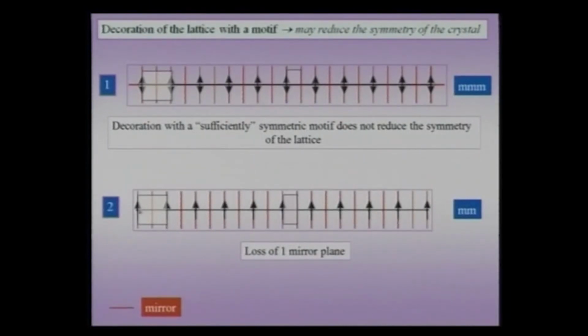Vertical mirror 1 remains, vertical mirror 2 remains, the translational symmetry still remains. Therefore, in shorthand I can write the symmetry of this lattice, or this crystal to be more precise, as T MV1 MV2, or in shorthand notation as MM symmetry. The MH, the horizontal mirror, has been destroyed and the crystal has only MM symmetry.